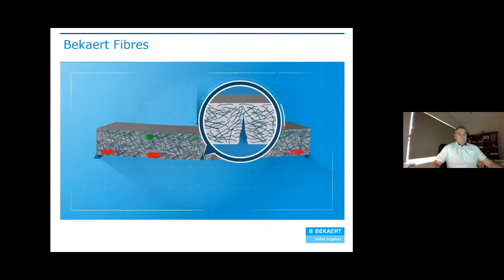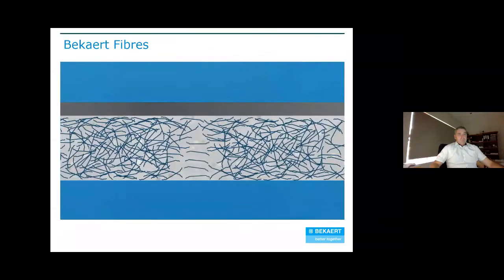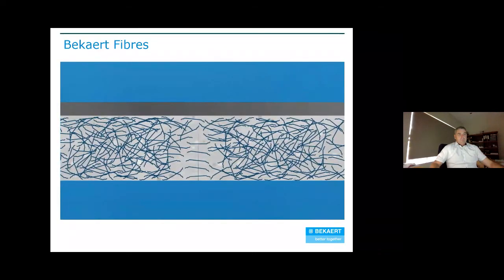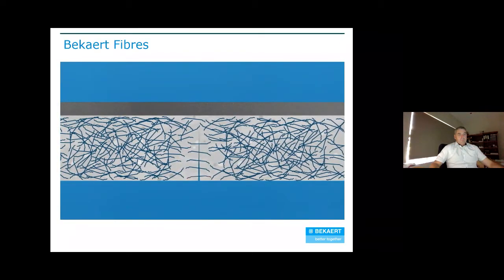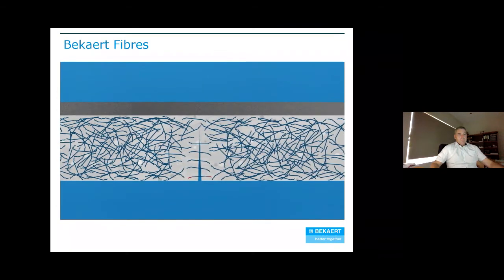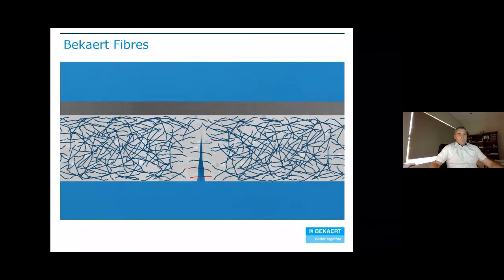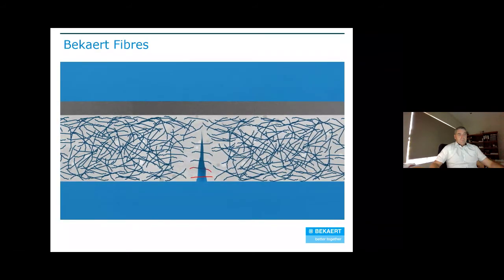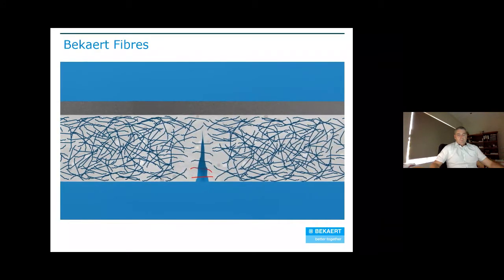Steel fiber interacts within the concrete matrix, absorbing tensile stresses at any point and in any direction. As a result, steel fiber picks up small cracks much faster than traditional reinforcement. When a crack occurs, the hooked ends of the fibers remain solidly anchored on each side of the crack, acting as a stress transfer media. Once the maximum bond strength with the concrete is reached, the pullout takes full effect. This enables the next fiber to take over, delaying cracks from growing.